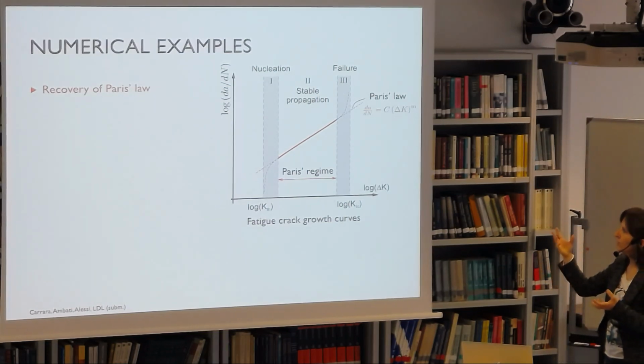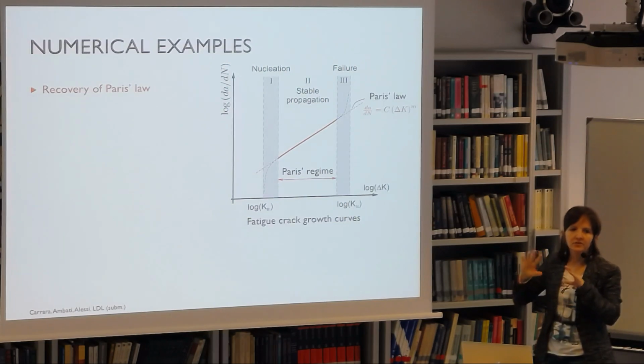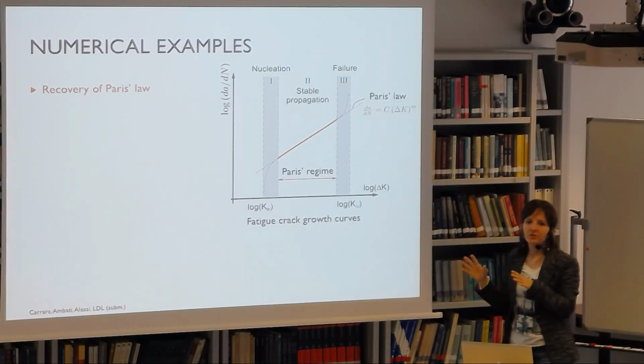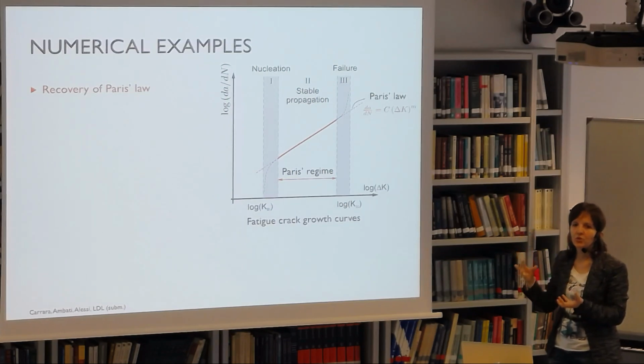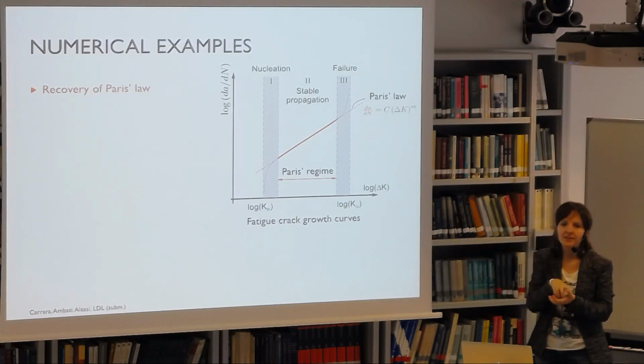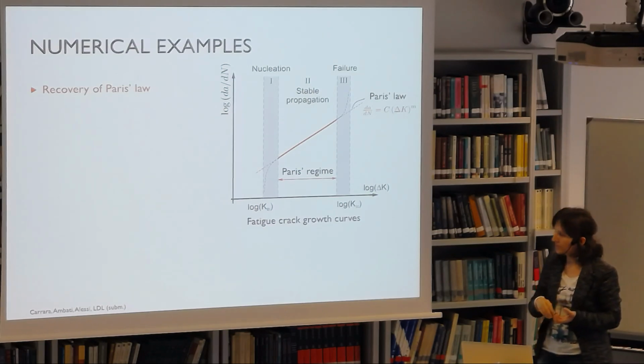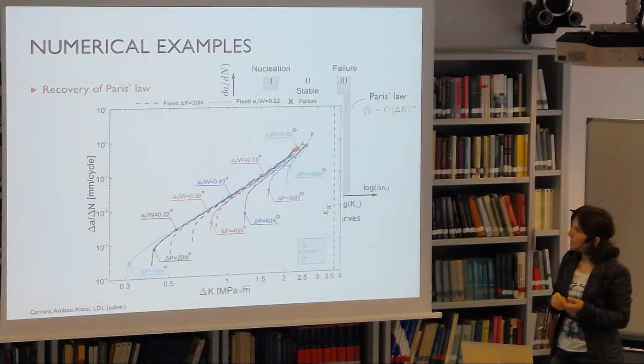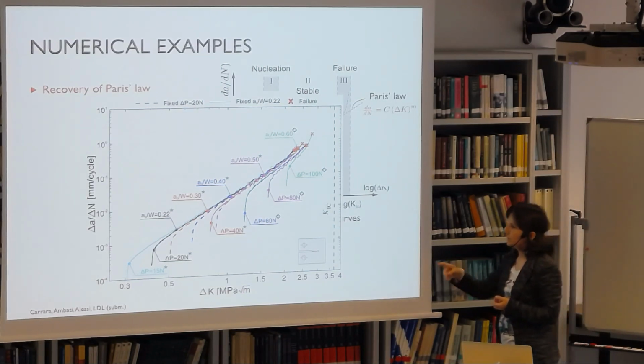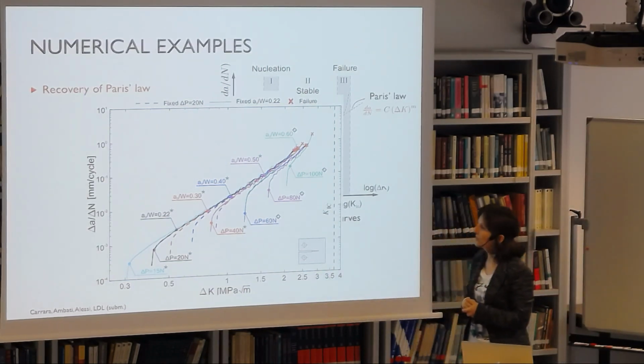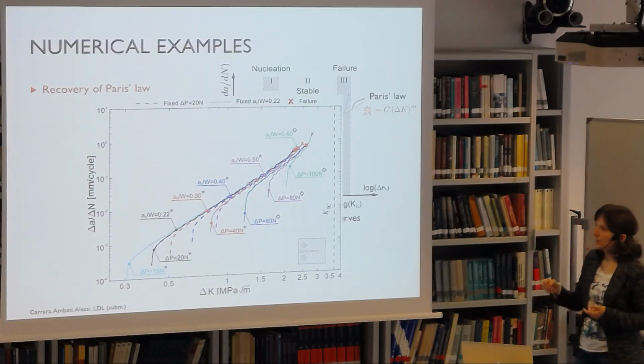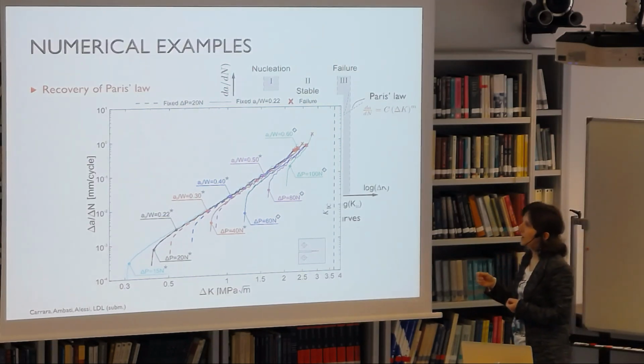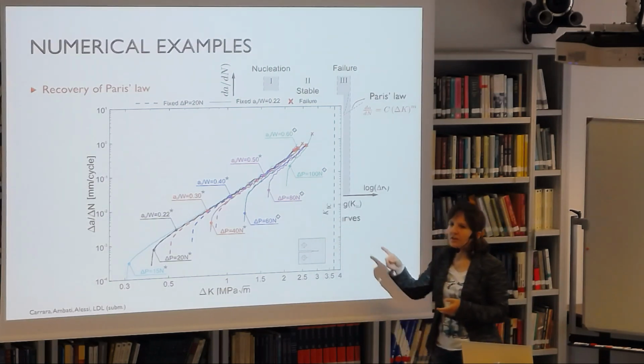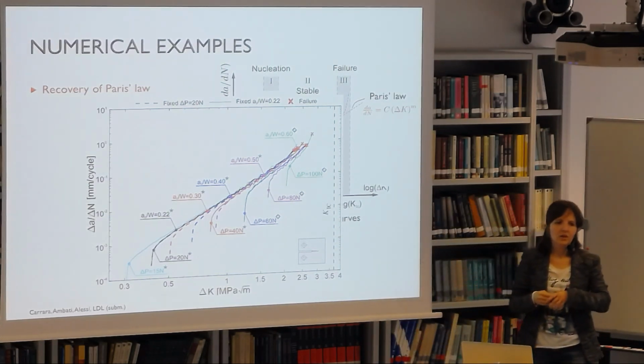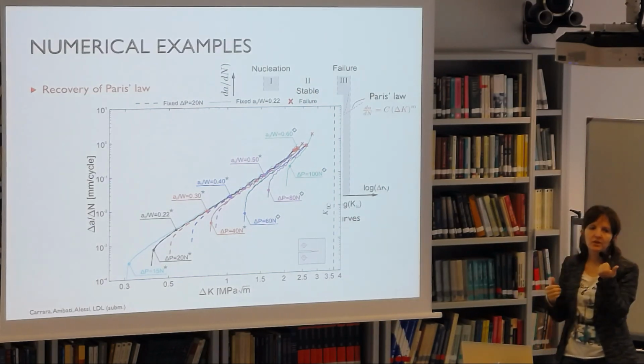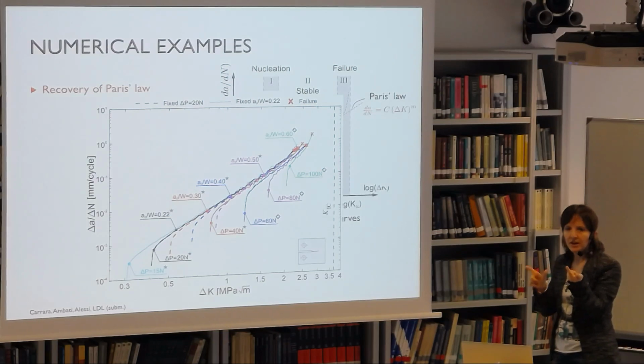So if you run experiments with different setups, you find the same C and m, because these are parameters related to a local behavior which is condensed in the information given by delta K, which is a local quantity, the stress intensity factor. And what we found out with our numerical experiments with the same type of compact tension specimen is that the behavior really resembles what we expect based on Paris. Of course, you can get the same delta K in different ways. It depends on P, the applied load, it depends on the crack length, and it depends on the geometry.